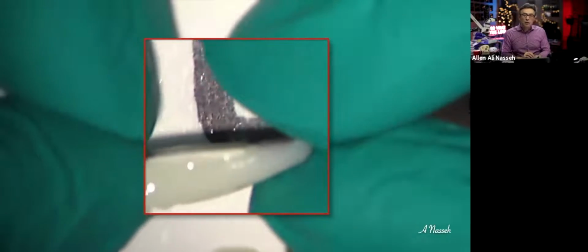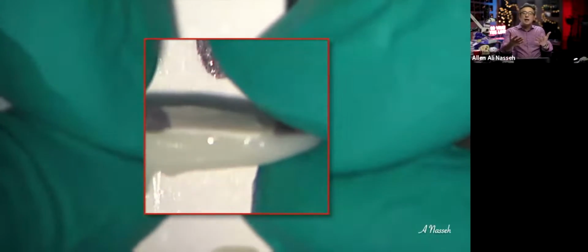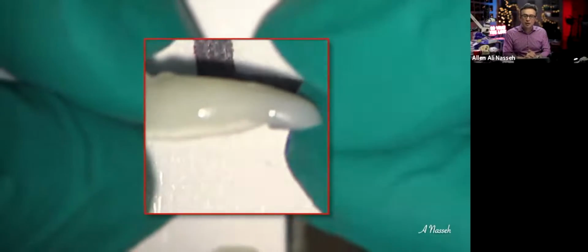the surrounding dentin. And you got to also make sure, if you're using a scope, to have an orange filter so that the initiation process does not start as soon as you start mixing it from the light from your microscope. So orange filter is very important. Otherwise, you're not going to get proper etching and bonding, and it's going to pull back. You're not going to get proper adhesion.